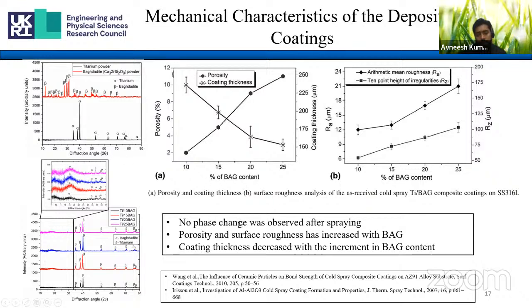Then with the increment in baghdadite percentage, we see that porosity and surface roughness are increasing constantly. However, the coating thickness has decreased. The reason for that can be that when the ceramic baghdadite particle strikes onto the titanium particle, or the ceramic particle itself, or the substrate, it either fractures or undergoes very little plastic deformation. This leads to some voids around the splat boundaries and causes the formation of a porous coating. So that's why with the increment in baghdadite content, the porosity has also increased.